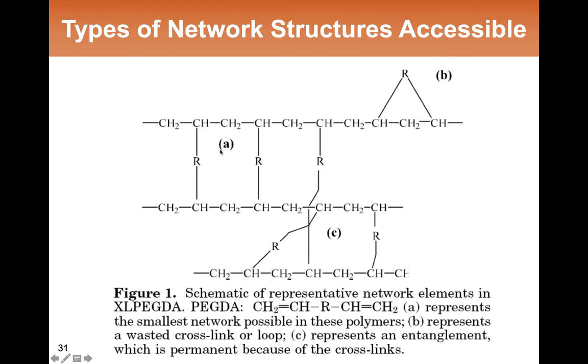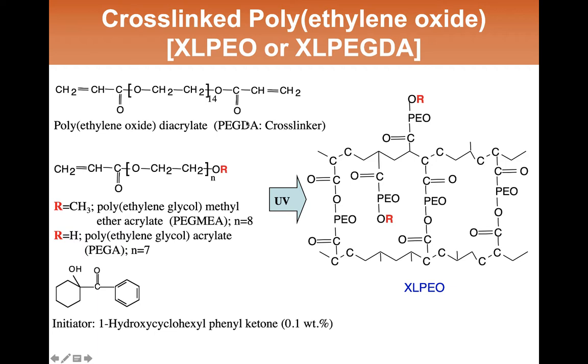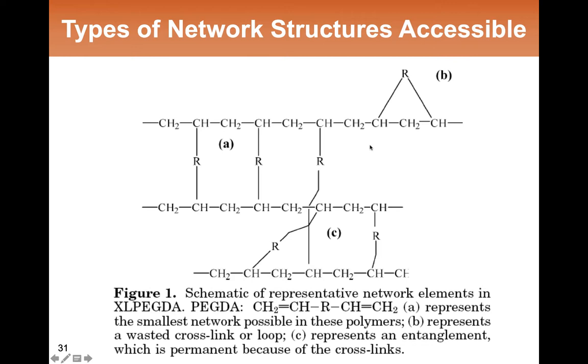However, there are also possibilities to form defects. One would be where the cross-linker, as it's polymerizing, instead of cross-linking with another chain, basically reacts with itself and forms what's called a loop, and that would be a wasted cross-link. There can also be entanglements formed between the cross-links connecting various chains, and that can represent a permanent entanglement because of the cross-linking.